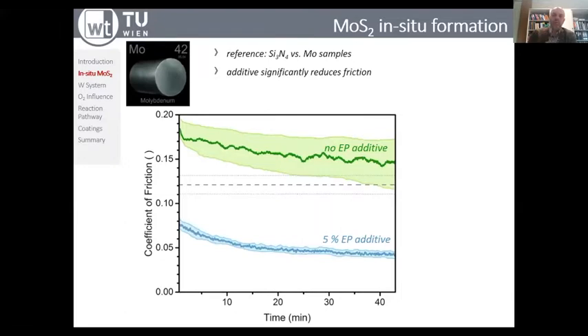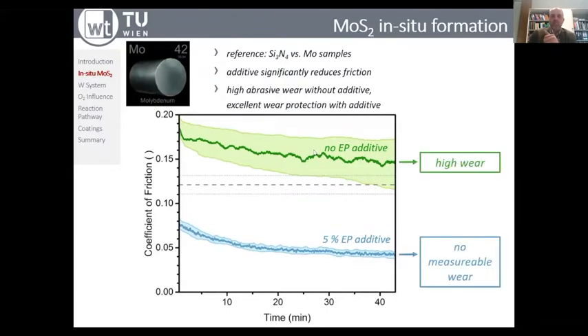On the one hand, you're looking at the situation with no EP additive at all. On the other hand, you are looking at the situation with 5% of an EP additive. And it's rather remarkable to see what happens when you add 5% of an EP additive. The friction coefficient drops significantly by just adding 5% of the sulfur source. On the one hand, we have very high wear. On the other hand, we have nearly no measurable wear. You can even see that for no EP additive, there are a lot of oscillations and fluctuations in the frictional signal. Whereas for the blue curve, for 5% EP additive, apart from the fact that we do not really measure wear, the curve is rather smooth, with not so much oscillation. So basically, the formation of MoS2 under these conditions is working.